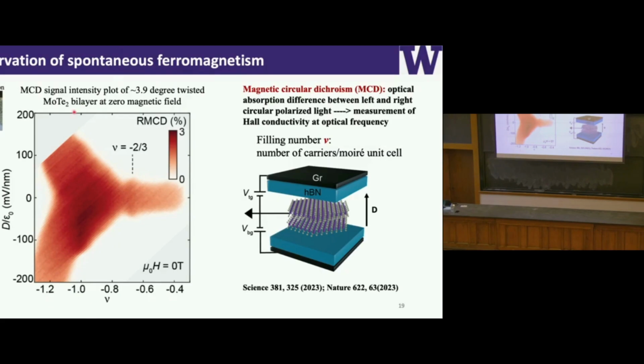What I show you here is the measurement of circular dichroism as a function of the electric field across the sample on the vertical axis, and the horizontal axis is the filling number, meaning the carriers per moiré unit cell. The color scale here, if you see a red color, means there's a non-vanishing MCD signal. It's an indication of ferromagnetism. So you can see that within a large phase space of electric field and filling number, we have a non-vanishing MCD signal. That's an indication of ferromagnetism. This ferromagnetism comes purely from the carrier-carrier interaction. It's a Stoner type of ferromagnetism.